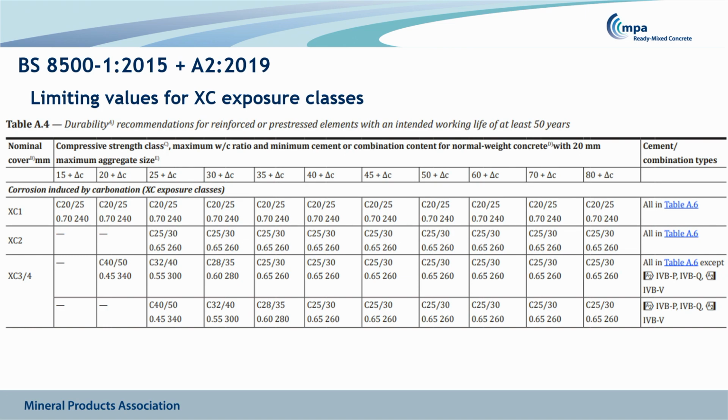And then there was concern that if we highlight that some cements carbonate rapidly, there would be people who would specify them for that very purpose and say, hang on a second, we have a low clinker, low carbon cement, and it absorbs CO2 rapidly. This must be a good thing, which could be problematic. So this table became very difficult to produce, trying to fit the cements all into this table.